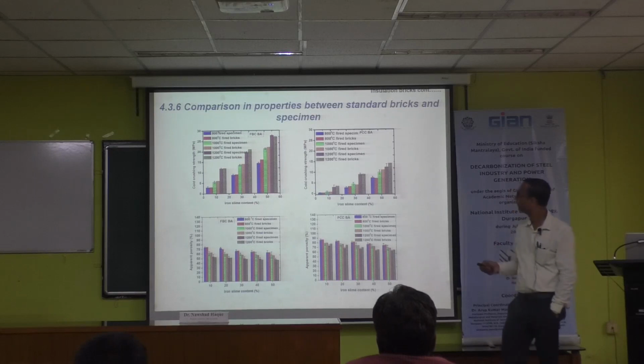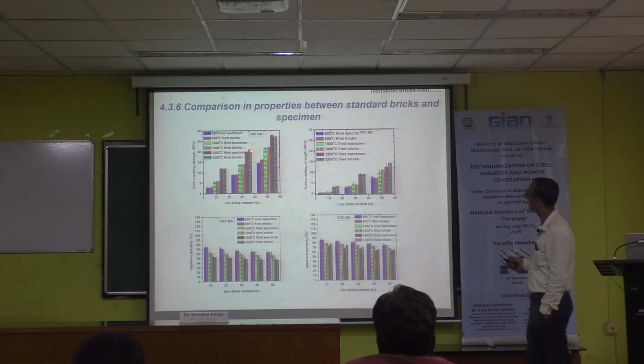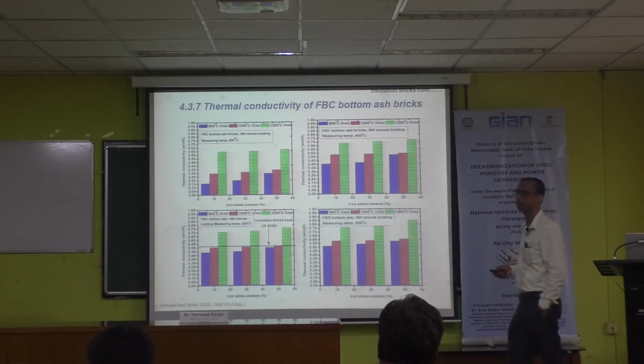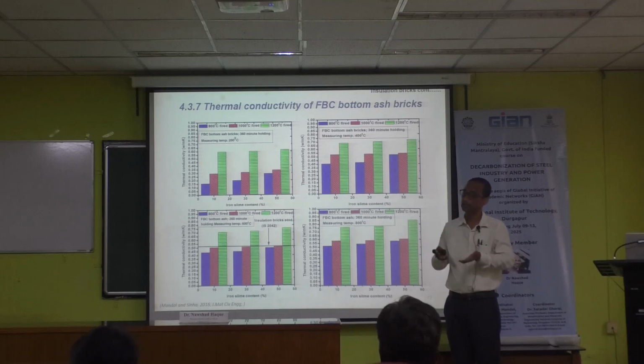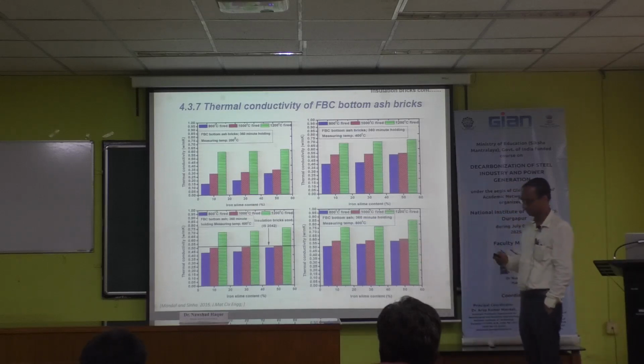Then we compared the FBC bottom ash bricks and standard bricks. We identified the brick specimens fired at 1000, 1200, 1255, with iron ore slime up to 50%: 10, 20, 30, 40, 50%, in case of LPC and in case of PCC. We prepared the standard bricks and compared, because in laboratory tests sometimes you get good results, but when you prepare larger size bricks, sometimes they do not satisfy the target. Therefore, we prepared large size bricks. Thermal conductivity property is also required.